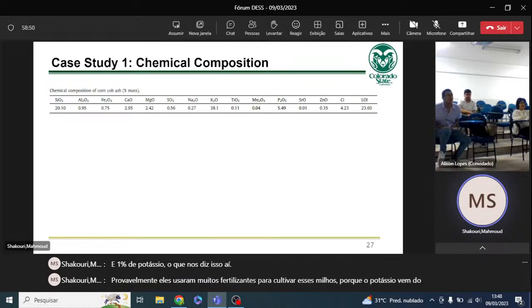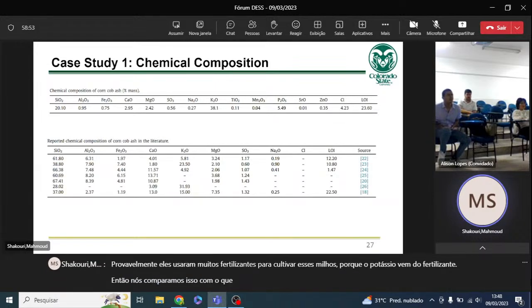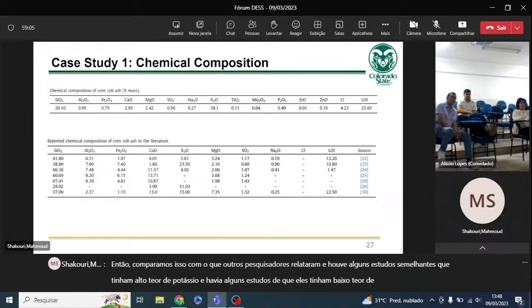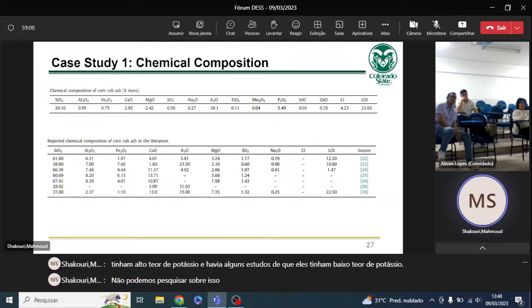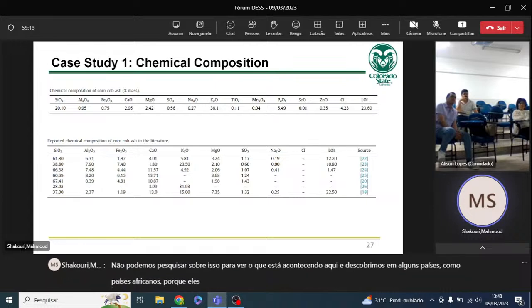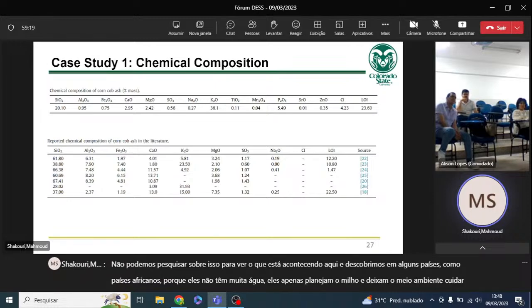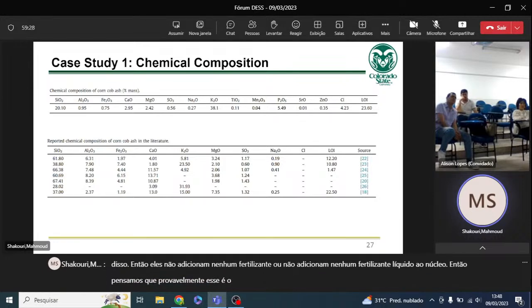So we compared that with what other researchers have reported, and there were some similar studies that had high potassium, and there were some studies that had low potassium. So we searched about it to see what's going on here, and we found out that in some countries, like African countries, because they don't have that much water, they just plant the corn and let the environment take care of it. So they don't add any fertilizer, or they don't add any liquid fertilizer to the corn. So we thought probably that's the main reason some of these ashes had a lower potassium content.